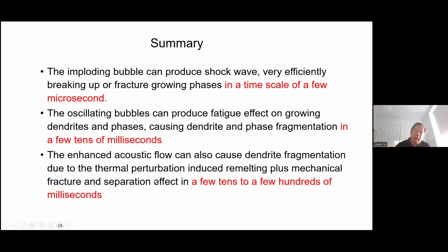And the relatively stable acoustic swirling flow acts on a much longer time scale. It also has a similar effect, but it acts on the structure in something like tens to a few hundred milliseconds. So that's the multiple scale issue, especially as these occur at different length scales. We are able to capture them with the brilliant synchrotron source, in particular at ID11 and ID19.